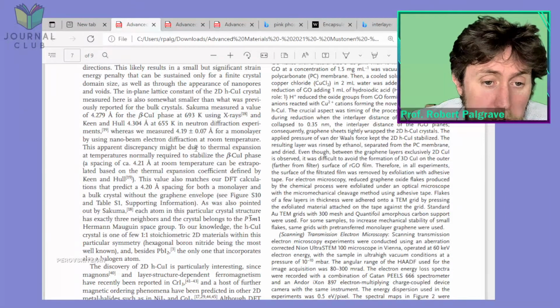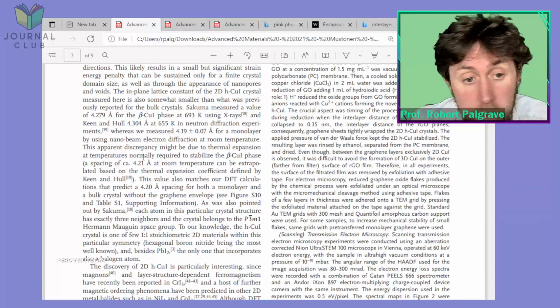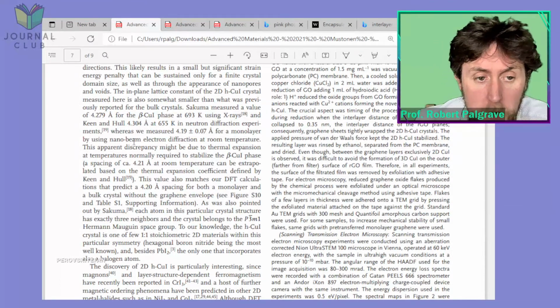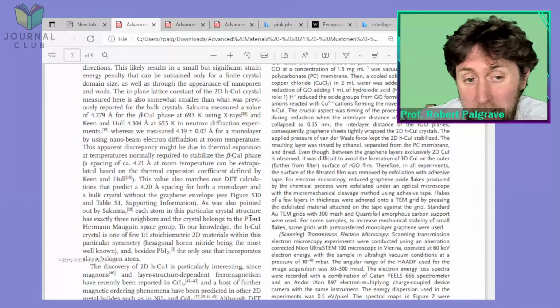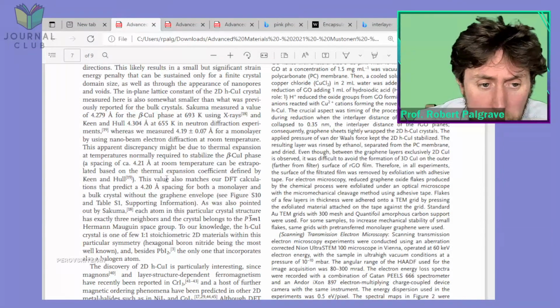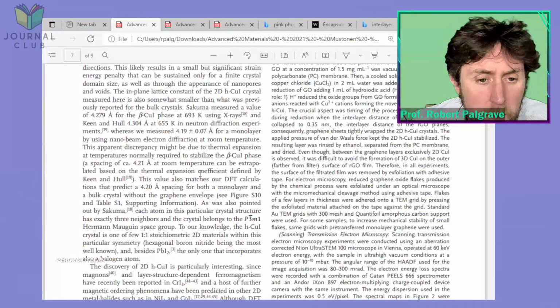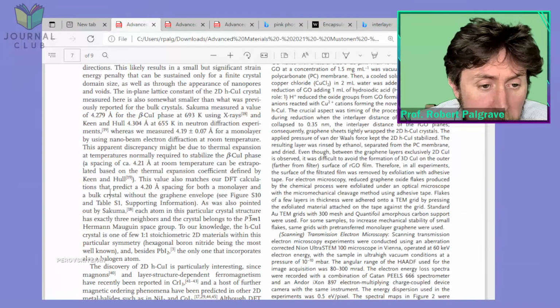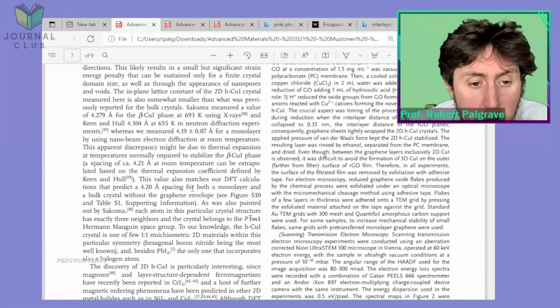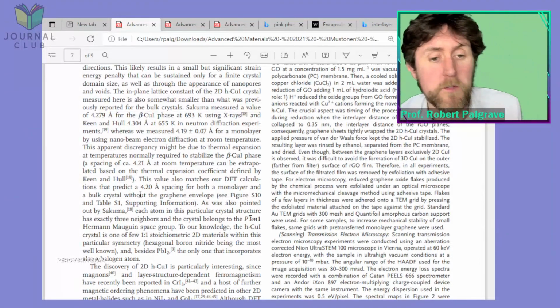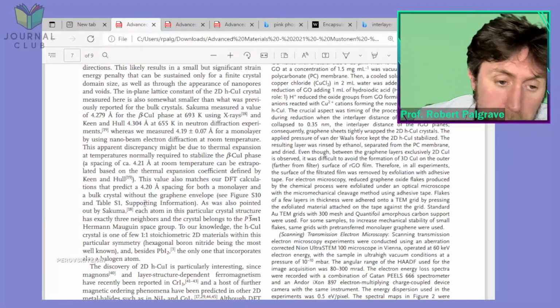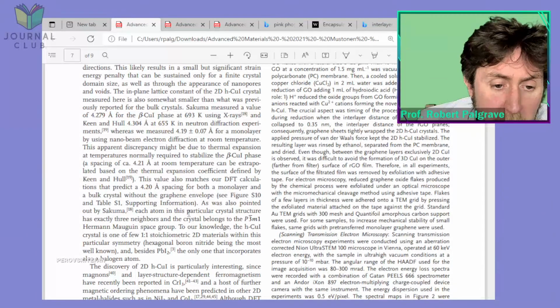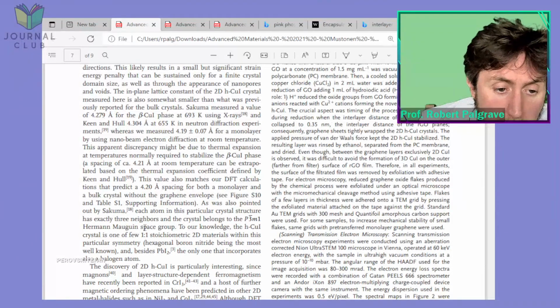The apparent discrepancy might be due to thermal expansion temperatures. Yeah, absolutely, of course. You're doing room temperature versus 655 Kelvin, and actually your difference is pretty small anyway, so I'm not too worried about that. This value also matches DFT calculations, which predict 4.2 angstrom spacing for both monolayer and bulk crystal without the graphene envelope. As also pointed out by Sakuma, each atom in this particular crystal structure has exactly 3 neighbors, and the crystal belongs to the P3 bar M1 HM space group.